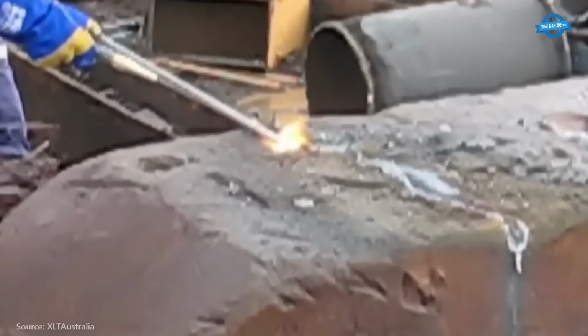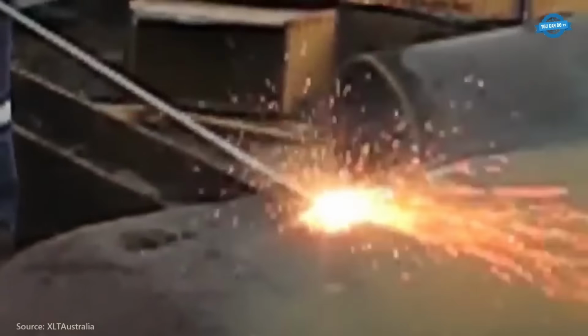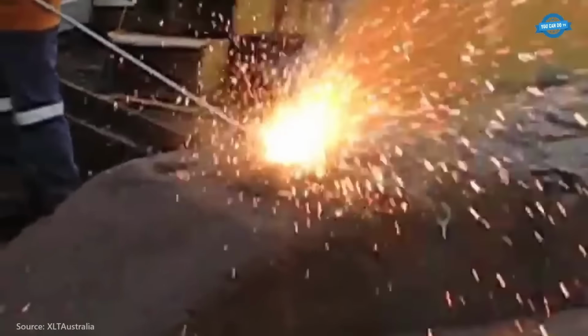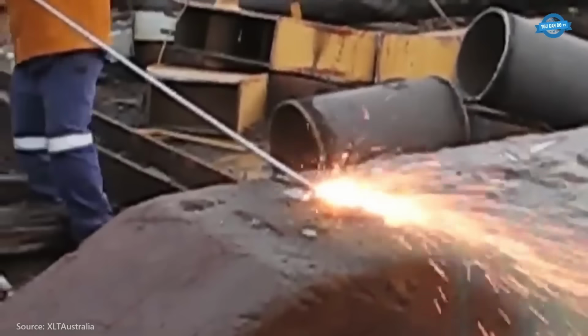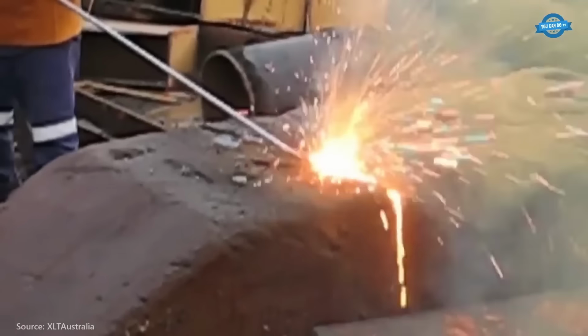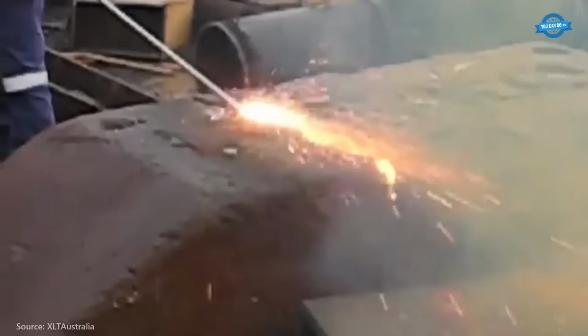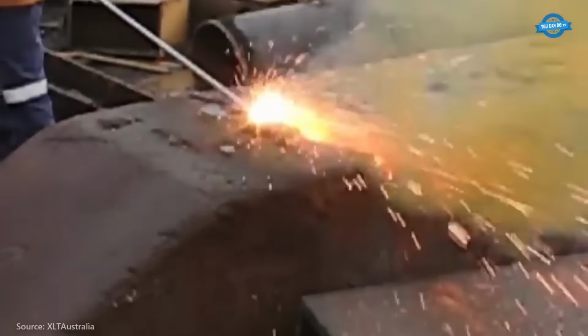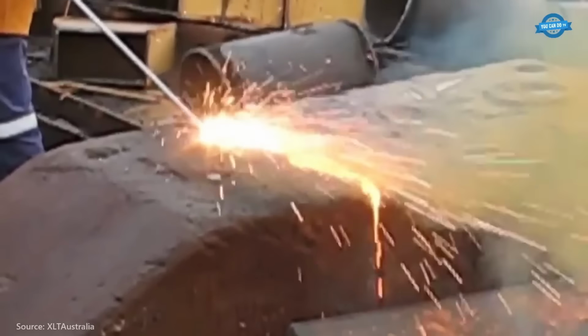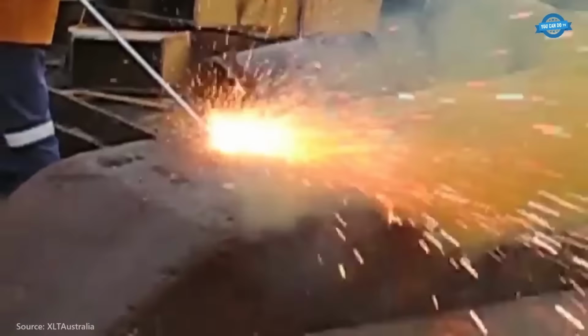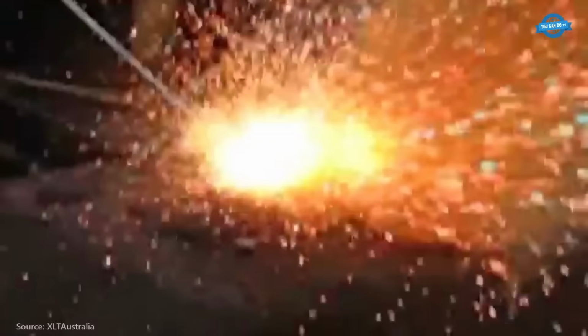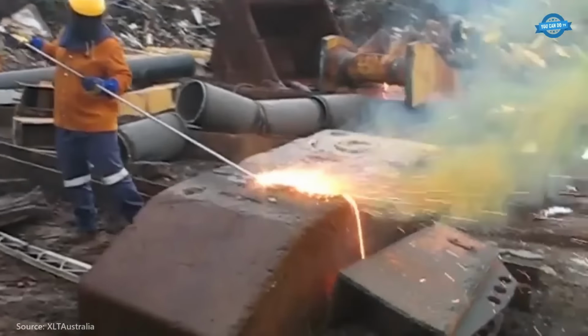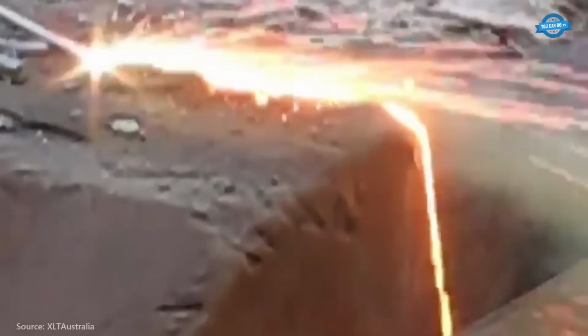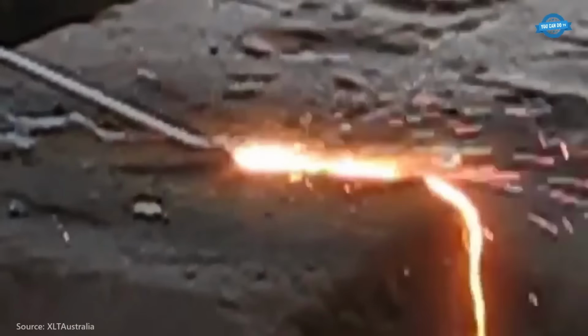Thermic lancing is a highly effective method for cutting through solid steel counterweights, utilizing extreme heat to melt and oxidize metal rapidly. A thermic lance, also known as an oxygen lance, consists of a hollow steel tube filled with alloyed steel rods. When ignited and supplied with pure oxygen, the lance burns at temperatures exceeding 4,000 degrees Celsius, 7,200 degrees Fahrenheit, easily cutting through thick and dense materials like steel counterweights.